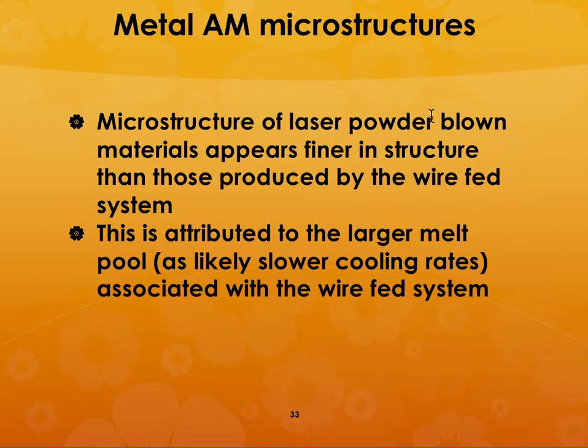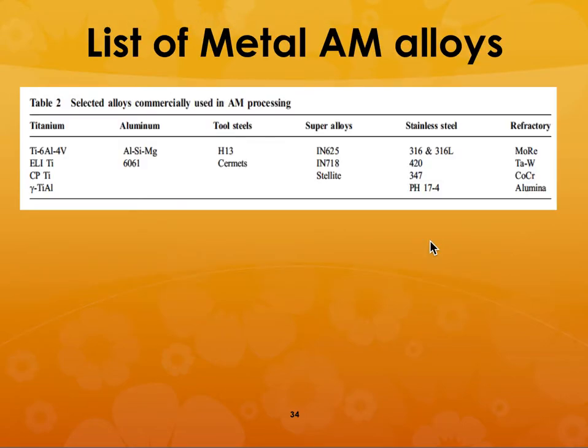So if you have a material that is being produced by a slower cooling rate, you are going to have a much coarser microstructure. In the laser powder blown, you are going to have heat deposition, as well as the extraction of the heat, at much faster rates. So that will lead to a much finer microstructure. So here are some examples. Again, this one reinforces what you saw in one of the earlier slides.